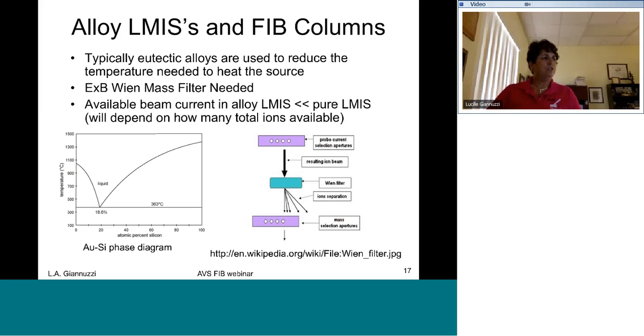Okay, you can also use liquid metal alloy ion sources to get different types of ions. And the way this works is basically you're using a eutectic alloy. So you're using a mixture of two or more materials in the liquid metal ion source. And then you use a filter, an E-cross-B Wien filter, to separate out which ions that you want or you need. So here's an example, and this is why you use a eutectic alloy.